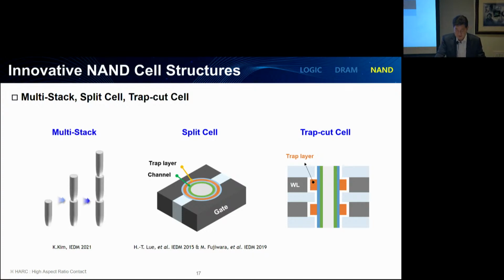In the multi-stack structure, we can mitigate the required process capability for HAR etch at the cost of additional repetitive processes. And in the split cell, the bit density can be doubled while maintaining the total stack height. However, an additional HAR etch is required. On the other hand, in the trap-cut cell, the vertical pitch of a single layer can be scaled by cutting the charge trap layer. We can greatly suppress the interference between neighboring cells.